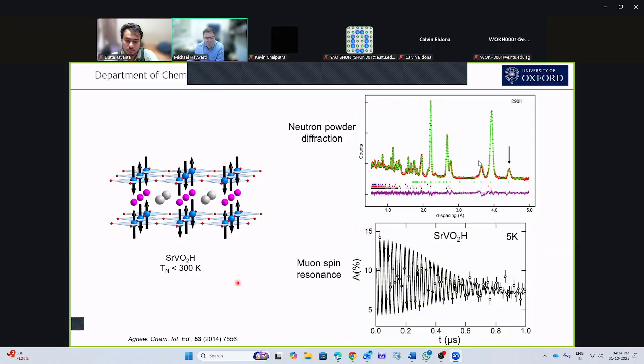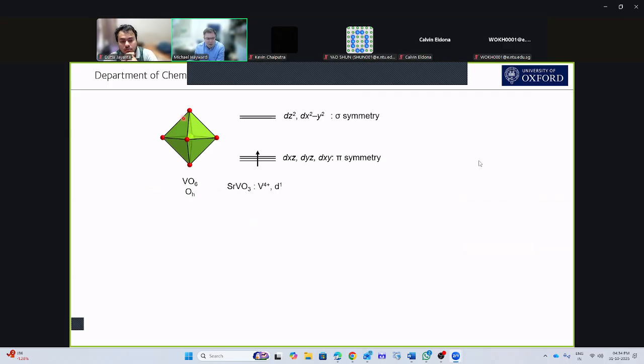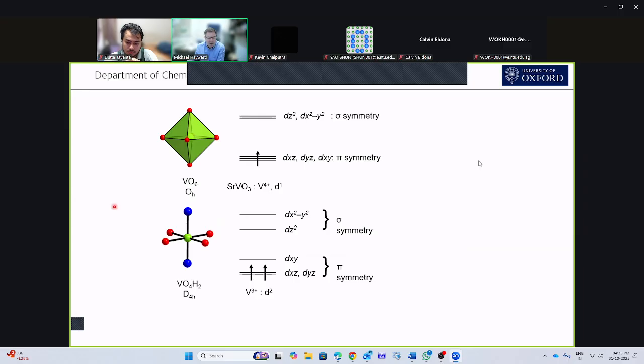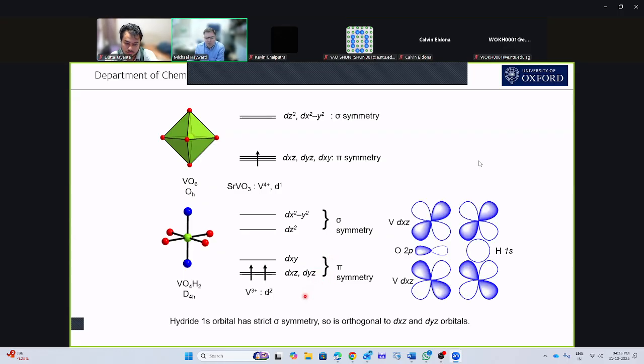But there's another interesting feature of the hydride ion. If we think about our starting compound in this reaction, this is SrVO3. This is a perovskite. It's a vanadium 4+ d1 case. So our d electron sits in our t2g pi symmetry orbital in a local configuration. When I exchange the oxide for hydride, my local coordination now becomes VO4H2. I'm now a vanadium 3+, so I gained an electron, and this electron now sits in these pi symmetry orbitals. The symmetry of this orbital is rather important because the hydride ion is a unique anion. It's the only anion of an atom that doesn't have any p orbitals, so it can't bond in a pi symmetry way. We can't bond with these pi symmetry orbitals here, whereas you can see an oxygen 2p orbital can. And that leads to a rather interesting physical situation.